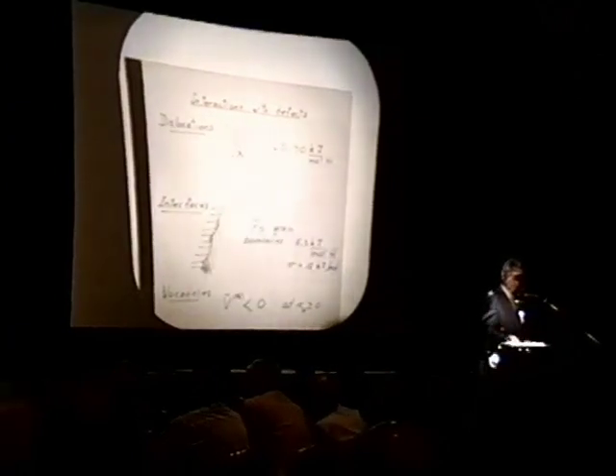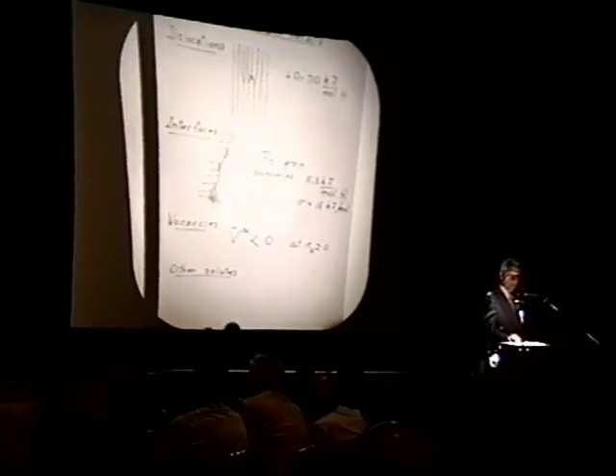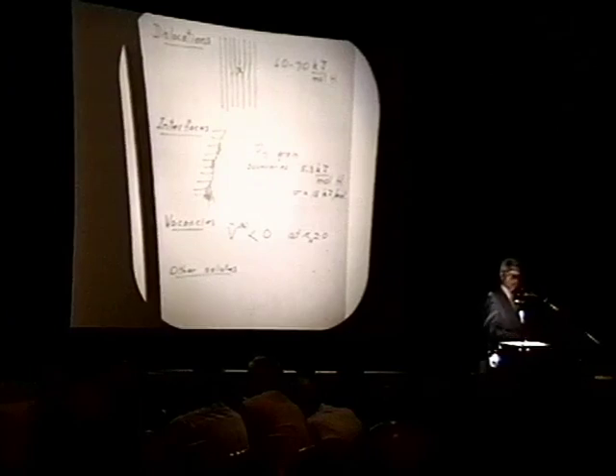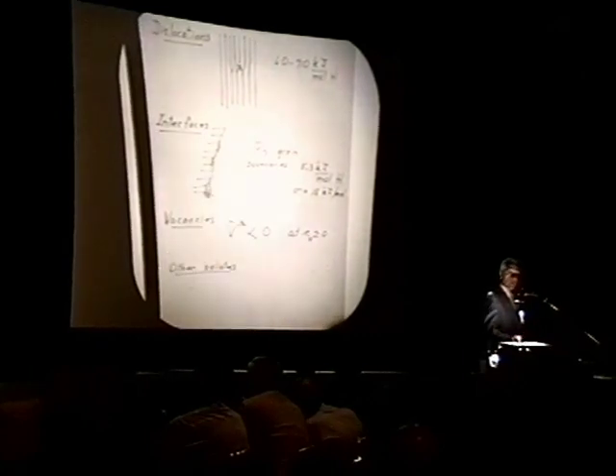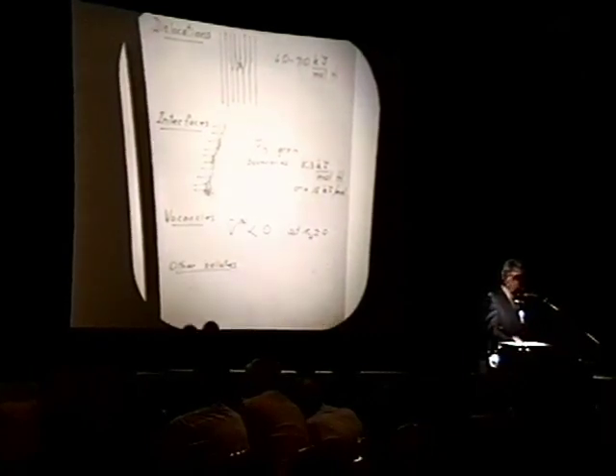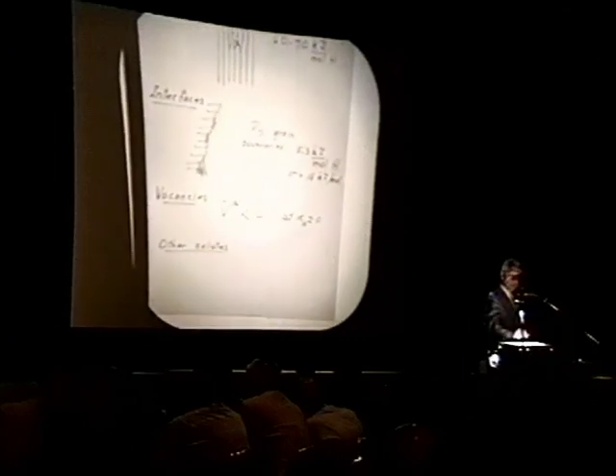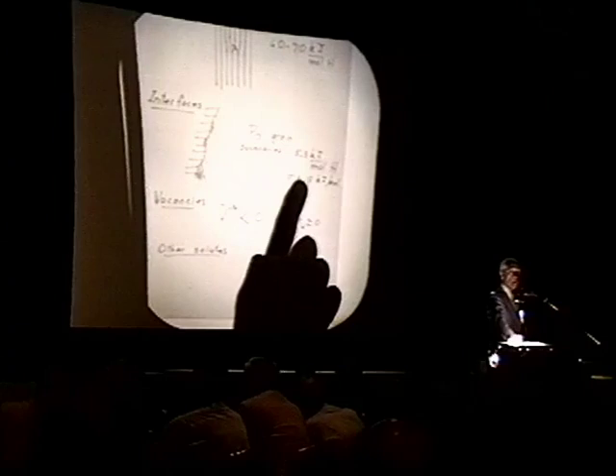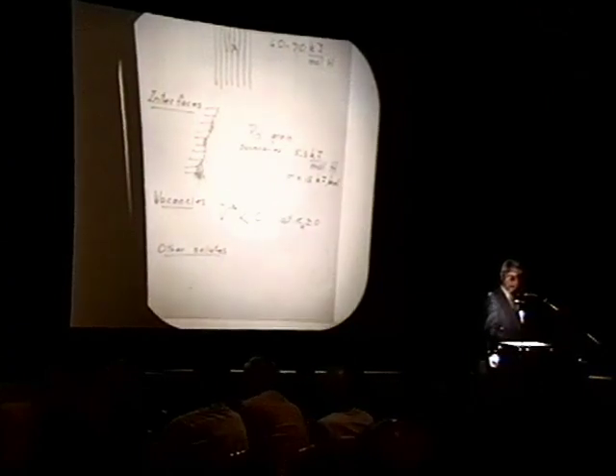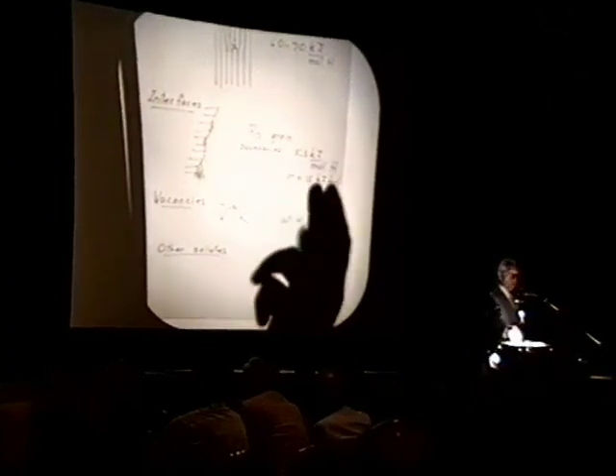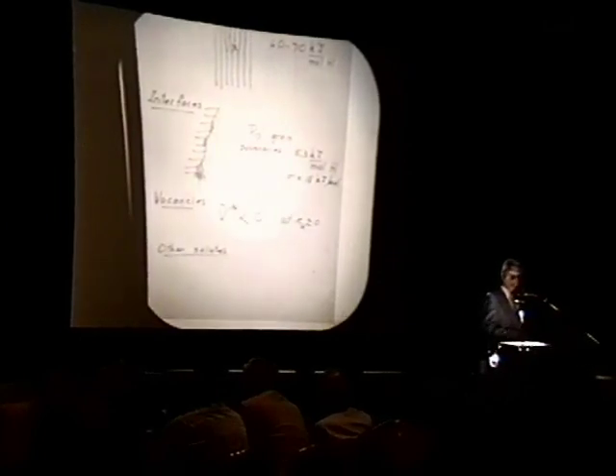So these you might call one-dimensional imperfections. There are two-dimensional imperfections in solids, all kinds of interfaces, both external surfaces as well as internal surfaces between phases, for example. And a grain boundary is also another type of two-dimensional interface. And there are well-known interactions. In the case of palladium with hydrogen, the interaction is about 5.3 kilojoules per mole on the average, with a Gaussian distribution of about 15 kilojoules per mole. You can see from this that therefore there are also some repulsive interactions as well as attractive interactions at grain boundaries.